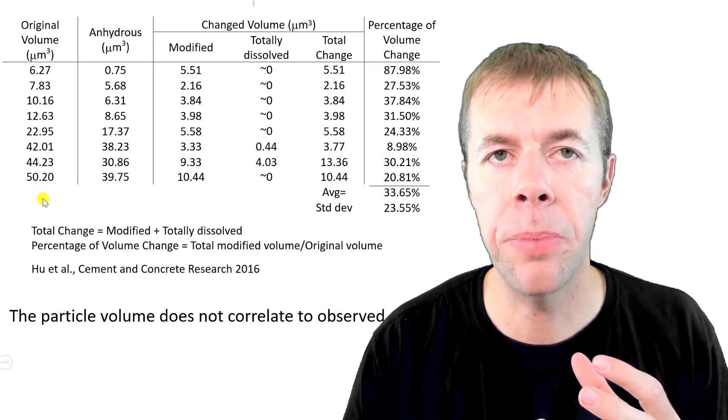I know what you're thinking. You know what, I bet it's a function of the volume. And here's the plot of about eight different particles. We're showing the volume that we've racked up here. Okay, this is the highest volume versus the lowest volume particles. And this is the percentage of change. And it's not necessarily tied to the volume. We've got smaller particles reacting about the same as larger particles. It seems to be kind of random and something we don't understand right now.